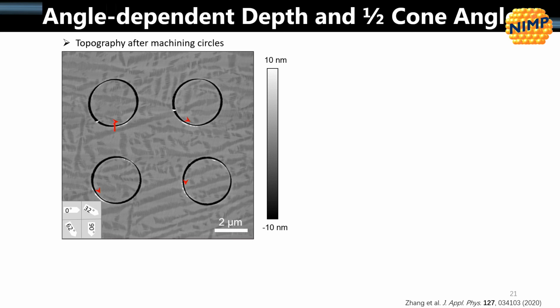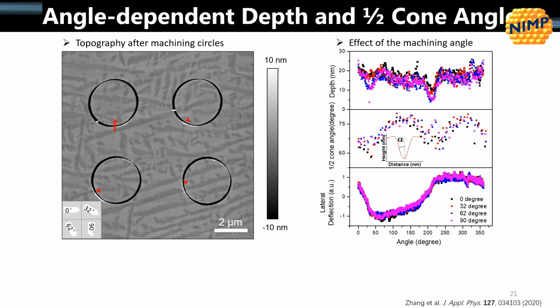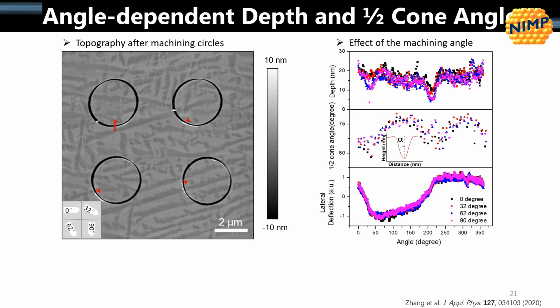This is a little time consuming, so it's drawing a circle, taking the sample out, rotating it, putting it back in, and understanding if there's an influence of the substrate or the crystallography. What we ended up seeing was that, for each of these different rotations, there's a location where it looks like it's the thinnest structure. So we can plot that, and we can also monitor the tip torsion, the lateral deflection, while we're doing this. You can see that the lateral deflection is close to zero, both at around 0 degrees and around 180 degrees. So a 0 degree scan is going to give you the narrowest structure, as indicated here by the half cone angle. We can do cross sections and see what is the actual half cone angle for these trenches that we've drawn, where the thinnest part would be the smallest angle.